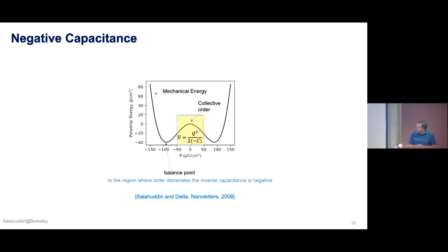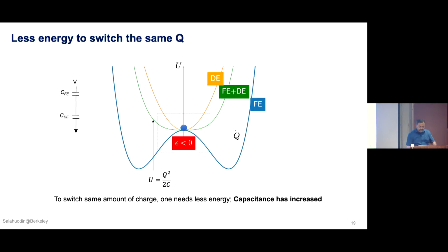If we look here, we can see that this middle region is an inverted parabola. So if I'm trying to fit a parabola here, I have to assume that capacitance is negative because Q square is positive. This allows us to have an interesting regime of operation for this material, where unlike conventional materials, the capacitance is negative. But we can also see that this region is not the minimum energy position for the material, so the material will not be stable there. So we have to find a trick to push it there, and I will say why we want to use this material in a minute.